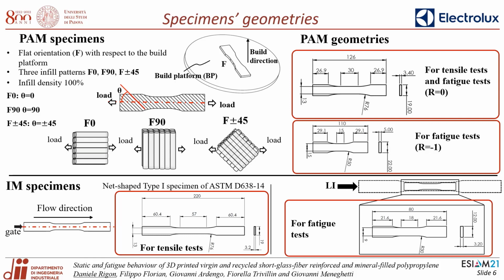So F0 means filaments oriented at 0 degrees with respect to the load applied, F90 oriented at 90 degrees, while F plus/minus 45 means that from one layer to another the deposition angle changes from plus 45 to minus 45 degrees. The printing strategy consists in depositing first one contour part and then filling the layer with the relevant infill pattern. Finally, the infill density parameter was chosen to be constant and equal to 100% for all specimens.